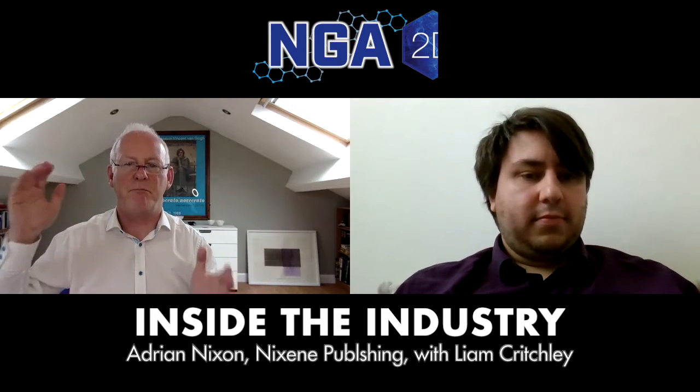You mentioned the quality required. Yeah, we're going to need very, very high quality. The industry standard at the moment is something called Six Sigma production, which means you've got 99.99-something percent good production, but there'll be a tiny amount of defects. Even if we applied Six Sigma production techniques to this, we'd probably end up with about 350 meters of defects somewhere in the tether. So we've got to completely rethink what we think of as quality.